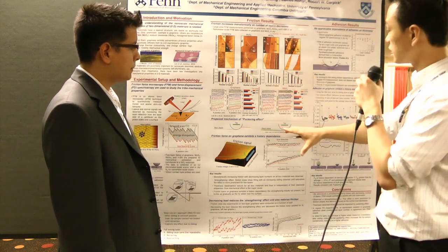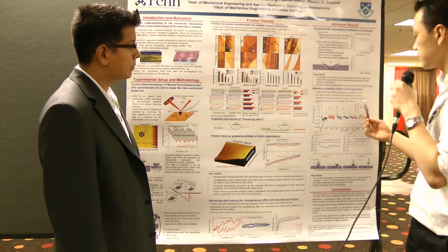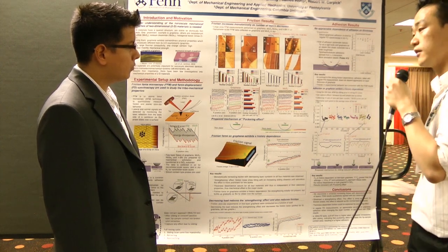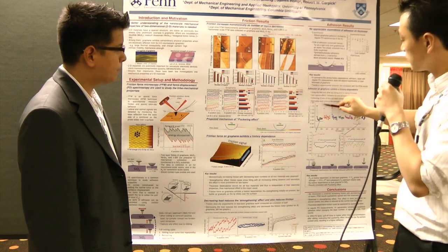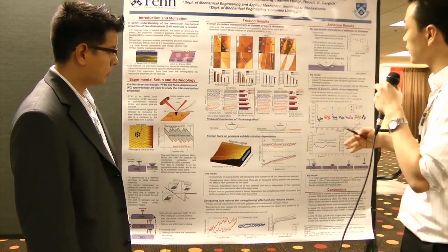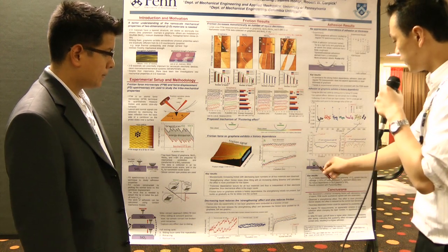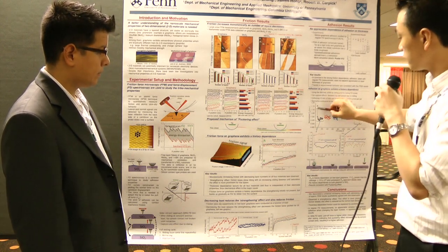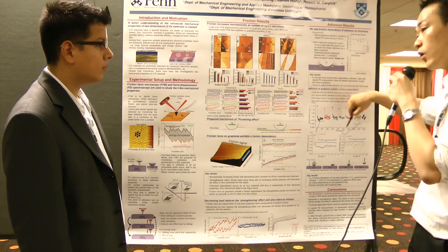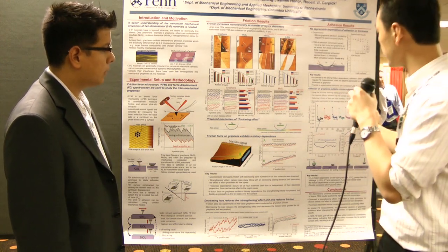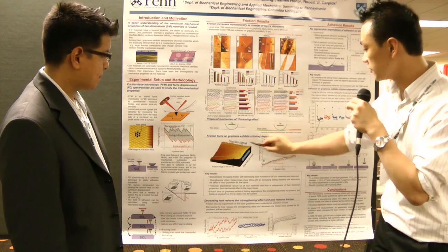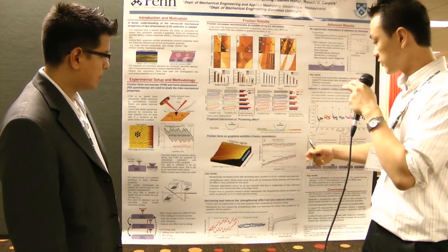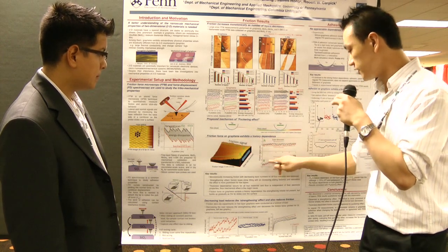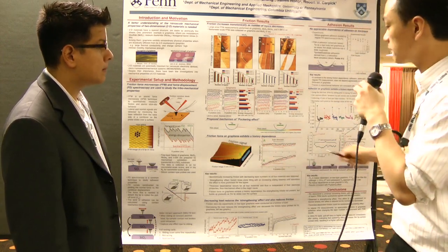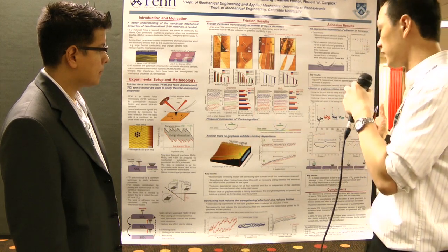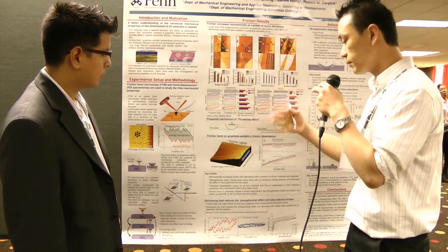Other than friction, we also measured adhesion, and that turns out to be also sliding history dependent. As you see here, we measure the pull-off forces of these materials, in this case just graphene, and after sliding, the first pull-off force is much higher than the subsequent ones. We think that's related to this effect too, because here you see at the beginning nothing is happening yet, but as the sliding proceeds, you see the effect. We think that is all caused by the puckering effect. So we find two kinds of evidence for this proposed mechanism.